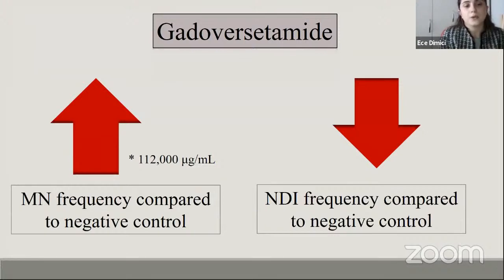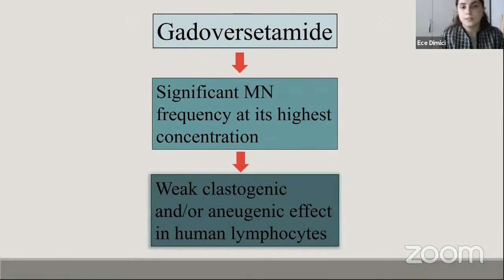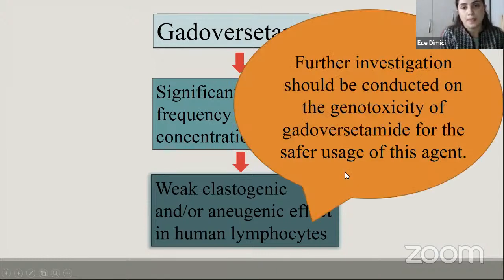Gadoversetamide in this study caused an increase in micronucleus frequency compared to negative control. Only the highest concentration was significant. If you look at the nuclear division index, gadoversetamide caused a decline compared to negative control, but none of these declines were significant. So we can say that gadoversetamide caused significant micronucleus frequency at its highest concentration. That is why it may have a weak clastogenic and or aneugenic effect in human lymphocytes. But of course, further investigations should be conducted on the genotoxicity of gadoversetamide for the safer usage of this agent.